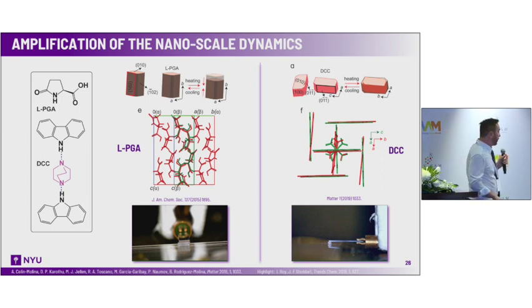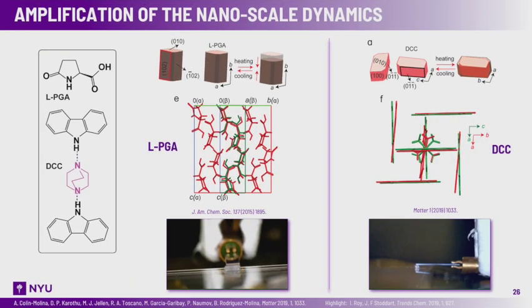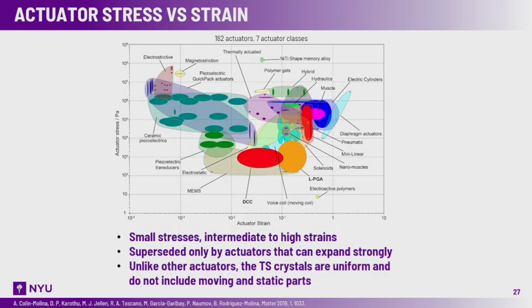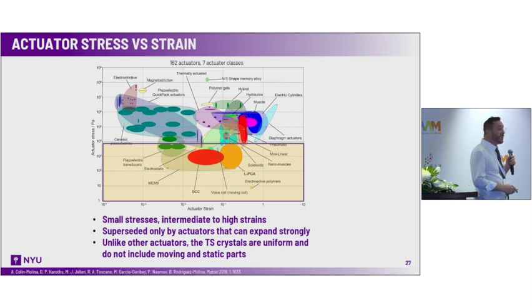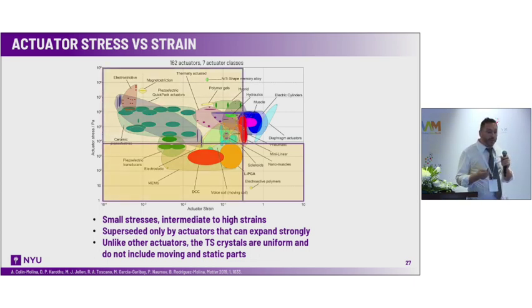There are some other examples where we use co-crystals, multi-component crystals, where we can also measure this force. You can see here on the right side, this is the co-crystal between two compounds. By direct measurement of the force, we can quantify it, and then compare it to some other materials. In this particular case, we find that the crystals have small stress and intermediate to high strains, but what is important is they are really, really light. They have low density, and also they are homogeneous. They don't include different parts like regular actuators. And this provides a much easier way to implement these materials into devices.